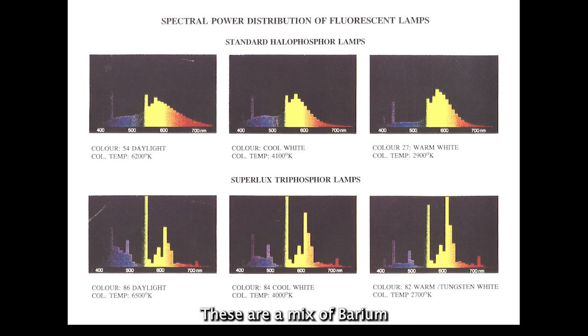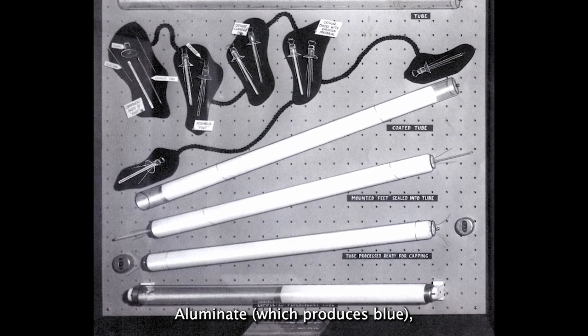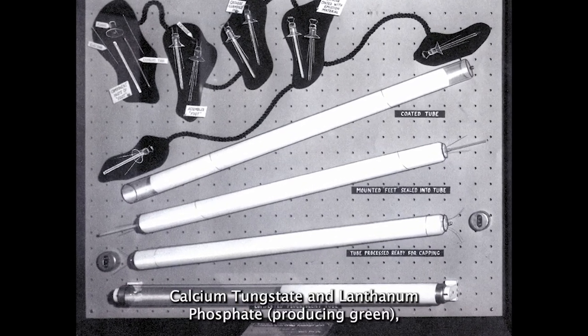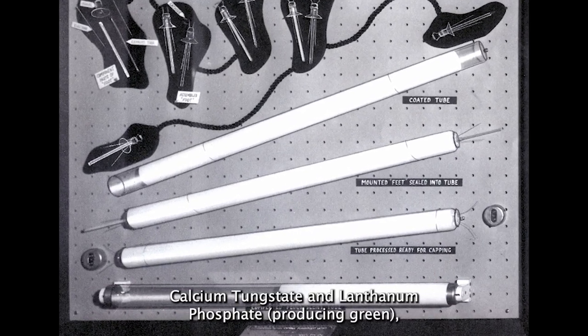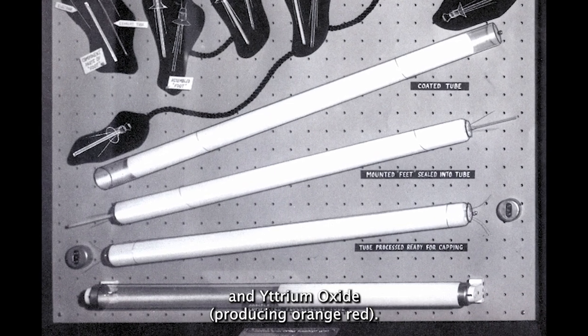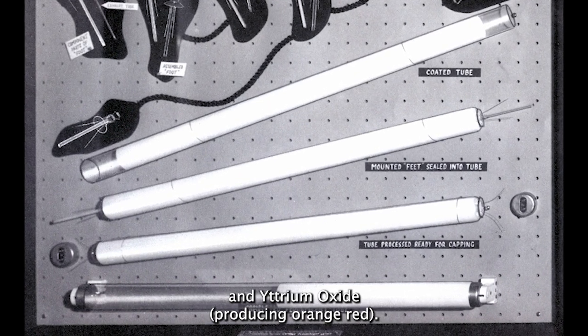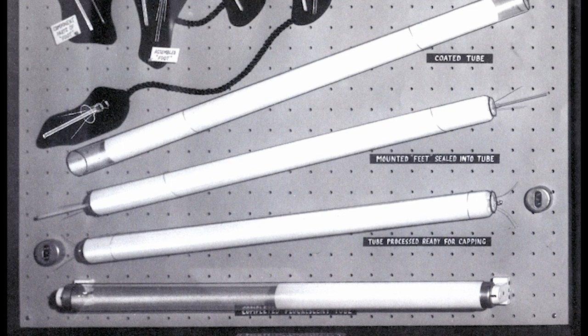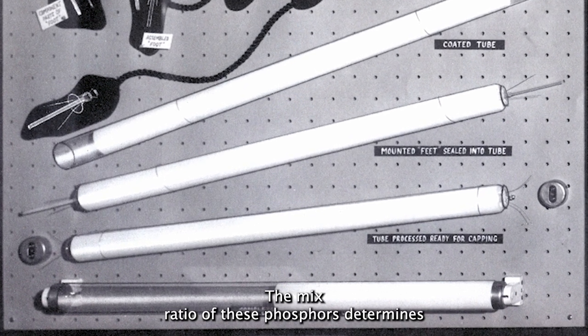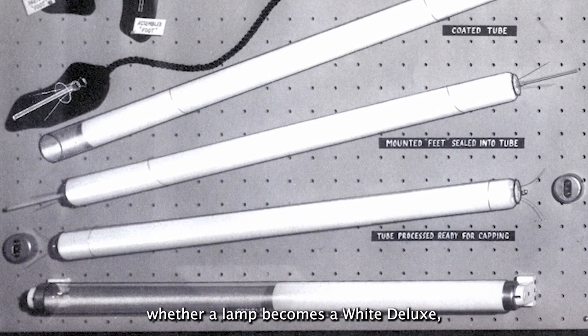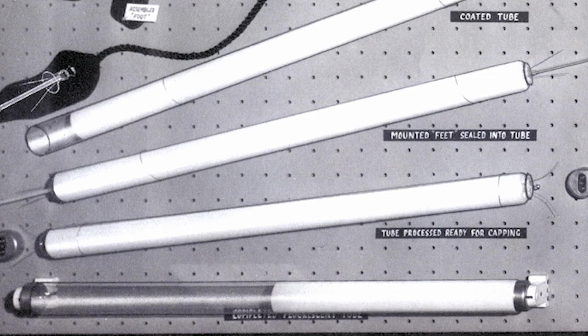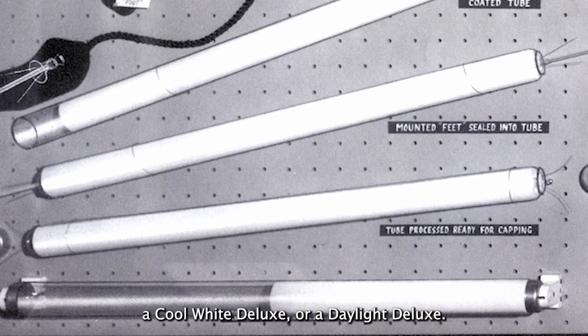These are a mix of barium aluminate, which produces blue, calcium tungstate and lanthanum phosphate, producing green, and yttrium oxide, producing orange-red. The mix ratio of these phosphors determines whether a lamp becomes a white deluxe, a cool white deluxe, or a daylight deluxe.